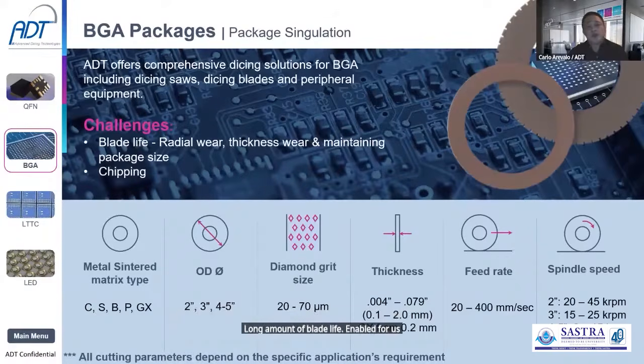For us to be able to achieve such a long blade life, you need to maintain the thickness of the blade, or what they call the lateral wear of the blade, to have a good balance with the radial wear. So that would maintain the package size during the package singulation. And another thing is the chippings, because PCB copper traces are very susceptible to peel-offs. So the optimal grit size and a combination of a lot of blade parameters is important in order to come up with the best matrix or the best formulation.